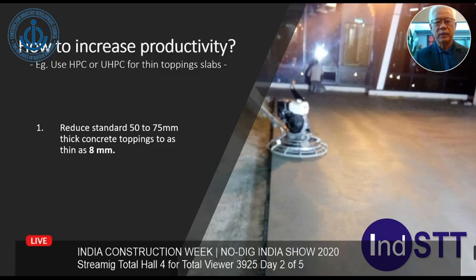So let's go back to the conventional concrete topping. In the market, normally you have to top up like 50 to 75 mm thick onto your existing substructures. If you use high performance concrete, probably you can bring it down to as thin as 20 mm. And if you use ultra high performance concrete, you can bring it down to as thin as 8 mm. And of course, you need some fibers to be added.